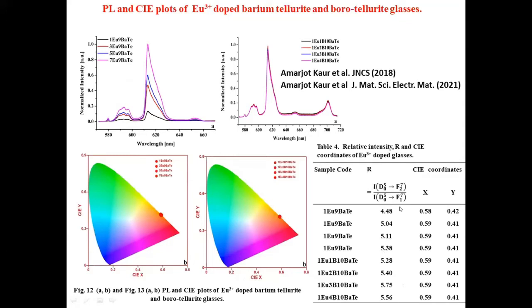So these are some of the spectroscopic data. You can see the XY coordinates. And again, in the case of the barium tellurite system, if you increase the europium oxide concentration, we don't see any concentration quenching effects. Even at 7 mole%, you see very strong luminescence, and the luminescence intensity at 7 mole% is higher as compared to the luminescence intensity of the 1 mole% sample.